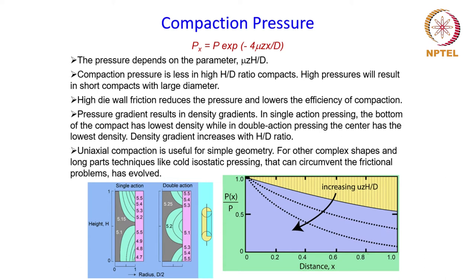Because of the difference in pressure at different depths in the compact, there is a pressure gradient from top to bottom. This pressure gradient is not desirable because it gives rise to a gradient in density as well. Therefore, the green density obtained in the compact will not be uniform throughout. If we look at density gradients for uniaxial pressing, this is how it looks for single action and double action pressing.